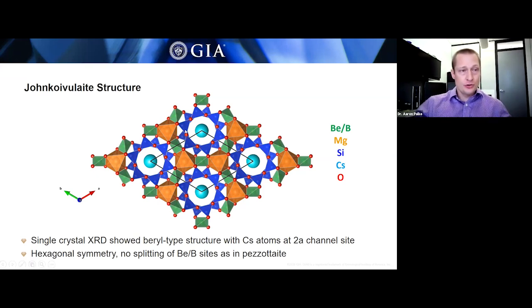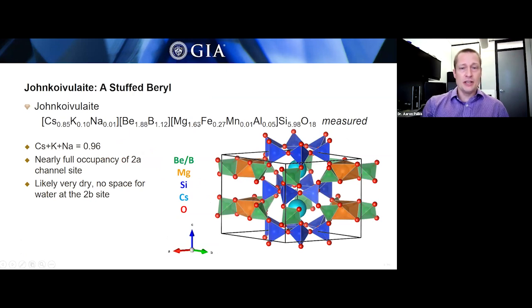They're connected to the other silica rings by these distorted tetrahedra of beryllium, or boron in the case of johnkoivulaite, and also these octahedra with magnesium occupying them. The thing about johnkoivulaite is we have boron and beryllium on these green distorted tetrahedra, and it's completely disordered. They're randomly distributed throughout that site. In addition, in the middle of these silica tetrahedra rings, there are these big atoms of cesium occupying these channel sites. And that's shown again here.